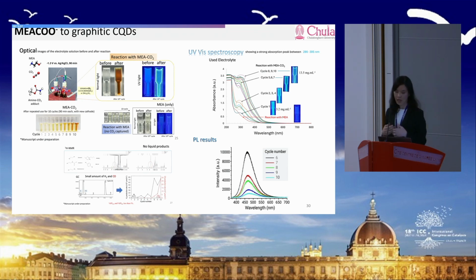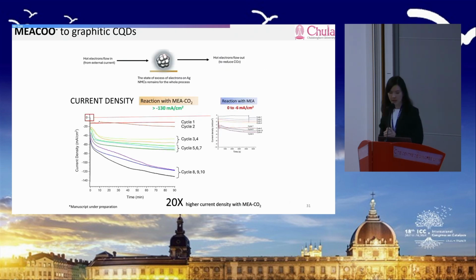In the end, the color of the electrolyte changes from a clear solution to a brownish color, and it exhibits very strong fluorescence properties, which is one indicator that we have carbon quantum dots in the solution. It's also proved by a strong absorption peak in UV-vis spectroscopy at around 290 nanometers, which indicates the presence of the carbon quantum dots. And also PL results. Okay, no liquid products and no change in the structure. Here I want you to pay particular attention to the current density.